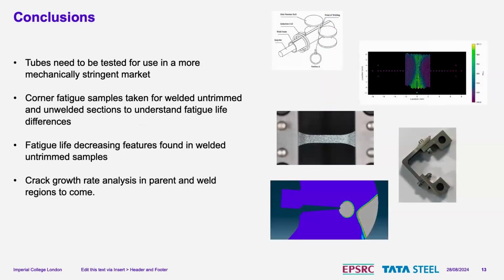So just to conclude, these tubes are needed in a more mechanically stringent market. They have more dynamic loading on them. I tested the hardness, and I took samples of the corner with the welding and determined the fatigue life of those. We found fatigue life decreasing features around the weld bead. And finally, I'm going to do some crack growth analysis as my future work. Thank you very much.